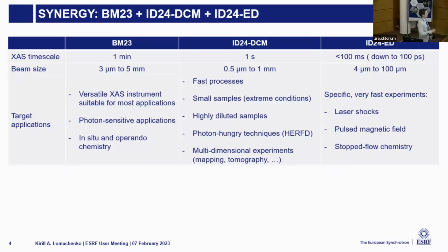So BM23 is a multi-purpose, versatile XAS instrument that can do basically anything if the time resolution, of the order of minutes per spectrum, and the flux, which is bending magnet flux, wiggler flux, are compatible with your tasks. So the main focus is pretty much anything that XAS can do. The focus is also on photon sensitive applications because we don't burn the samples very fast. So the tender samples survive. And this is often the case for catalysts, for chemical samples. So we do a lot of in situ and operando chemistry there.